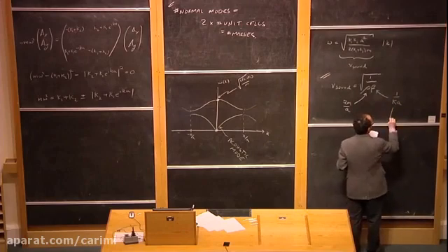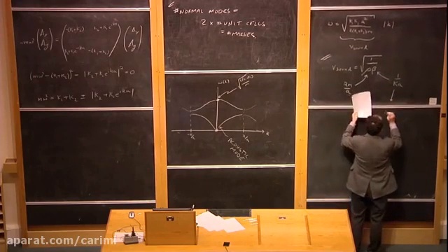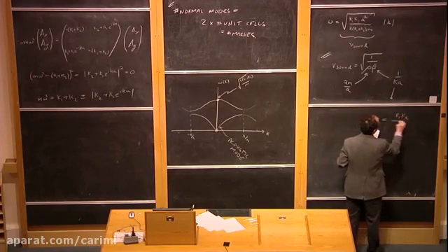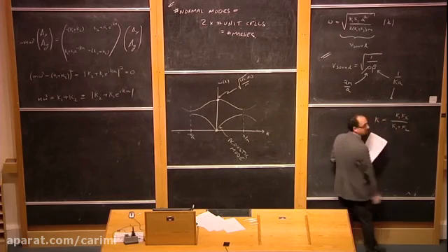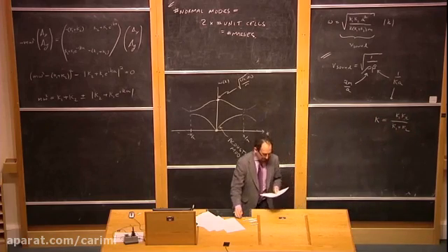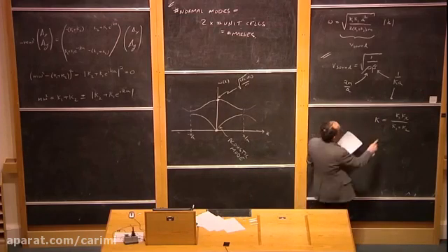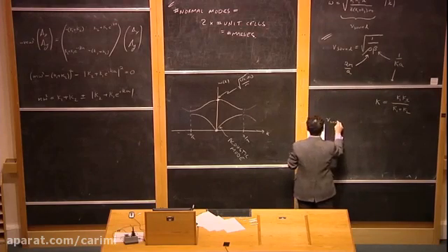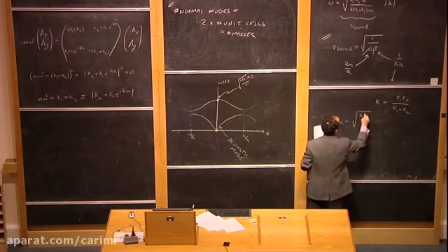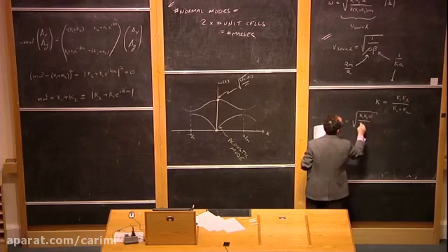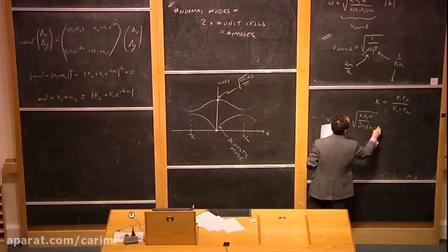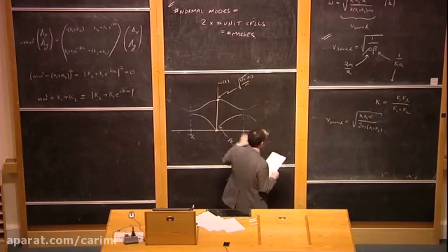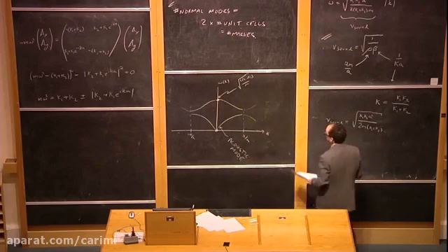And the spring constant, well, here the unit cell has 2 springs in it. And the spring constant for 2 springs in series is kappa 1 kappa 2 over kappa 1 plus kappa 2. Does that sound familiar? Remember that from first year? OK. So if we plug this and this and this into here, in fact, we get exactly the same result. V sound equals the square root of kappa 1 kappa 2 a squared over 2m kappa 1 plus kappa 2. So the hydrodynamic calculation gives you exactly the same result as we got by actually solving the system completely.